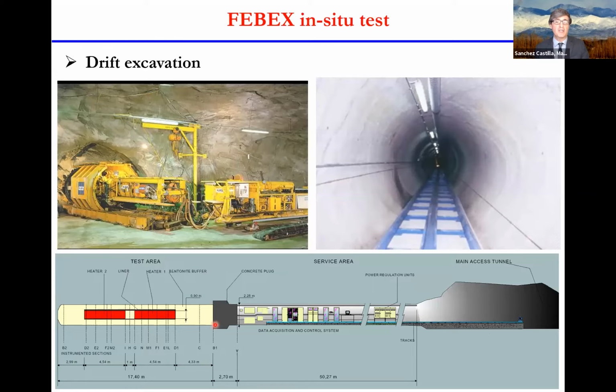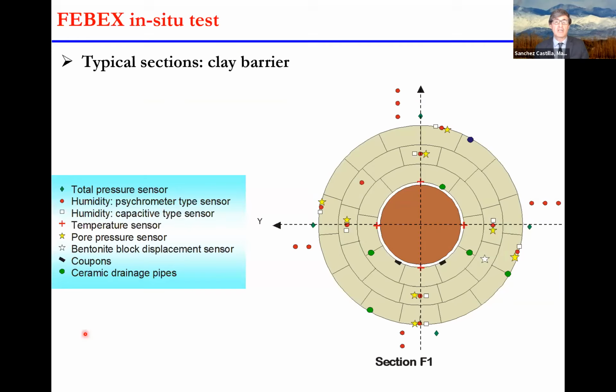The clay barrier is this yellow part. This is a concrete plug that isolates the heater from the rest of the gallery, in which we have all the instruments that allow us to track the evolution of the system. This vertical black line that you see here corresponds to instrumented sections, in which we have sensors of different types. We measure stresses, liquid and gas pressure, relative humidity, temperature, and other variables. And these are typical locations of the sensors in these different sections.